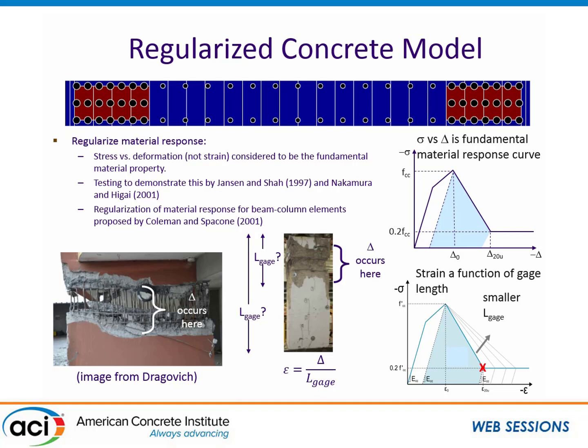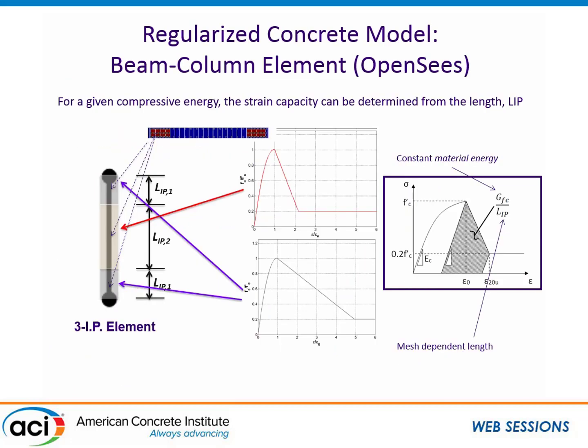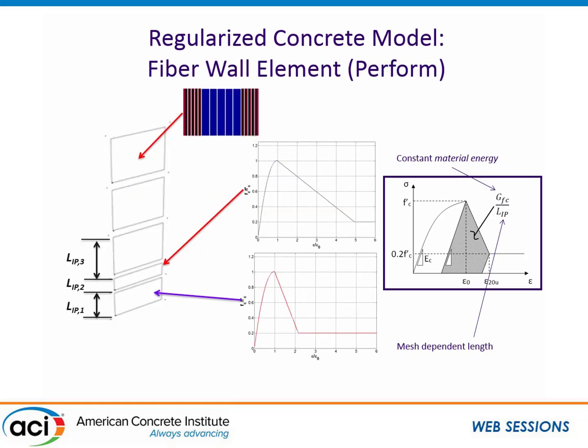The fundamental behavior of reinforced concrete failing in compression is a load versus deformation response, not a load versus strain response. If you think about this test specimen representing a boundary element — when you squash it, damage localizes and you get a certain deformation in that region. Dividing by one gauge length gives one strain; dividing by a different gauge length gives a different strain. Strain is a function of gauge length or element length, so you want your stress versus strain to be a function of L-gauge or L-element.